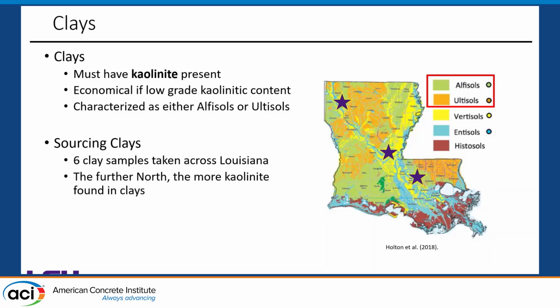It's typically most economical if you can use a clay that has a low-grade kaolinite content. If it has something, let's say, in the 90 to 100 percentile range, then there's going to be too high of a demand for it in other industries, such as the pottery and porcelain industry. These clays are typically characterized as Alfisols and Ultisols. And as mentioned previously, this is a Louisiana-based project, so you can see that Louisiana is truly covered with these clays of Ultisols and Alfisols.